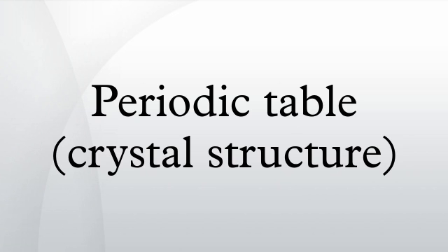Face-centered cubic has every third layer directly above and below each other, A, B, C, A, B, C, also termed cubic close packing, Fm3m, Pearson symbol cF4, Strukturbericht A1. Double hexagonal close packing has layers directly above and below each other, A, B, A, C, A, B, A, C, of period length 4, like an alternative mixture of FCC and HCP packing. Samarium-type packing has a period of 9 layers, A, B, A, B, C, B, C, A, C.